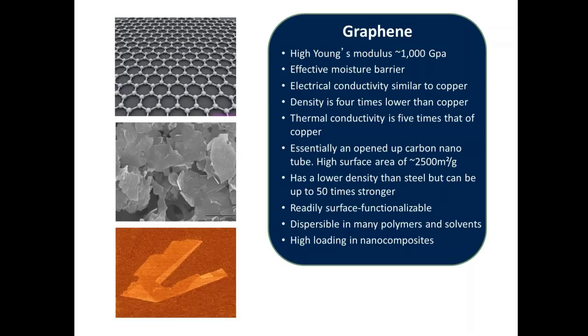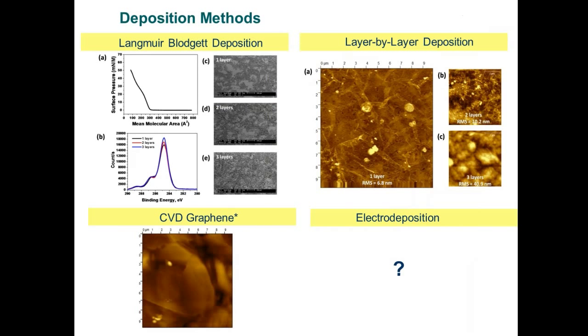All of these interesting measurements, of course, are related to the sample geometry or the way the material itself is oriented, meaning when we say something is stronger than steel, you have to take it with a grain of salt, meaning how was it actually measured. The properties of graphene are very different tangentially or in parallel with the plane of the graphene material itself.